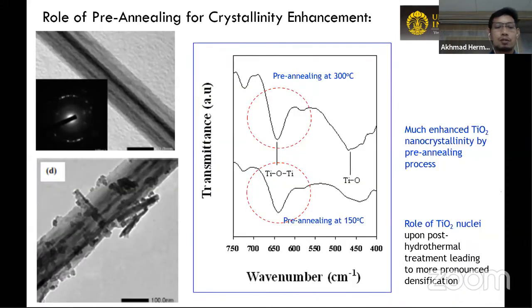This is also confirmed by FTIR. By increasing the pre-annealing temperature before subjecting to post-hydrothermal treatment, we can provide more TiO2 nuclei to be rearranged during the post-hydrothermal treatment. By using FTIR spectroscopy, we can confirm this. Next slide, please.